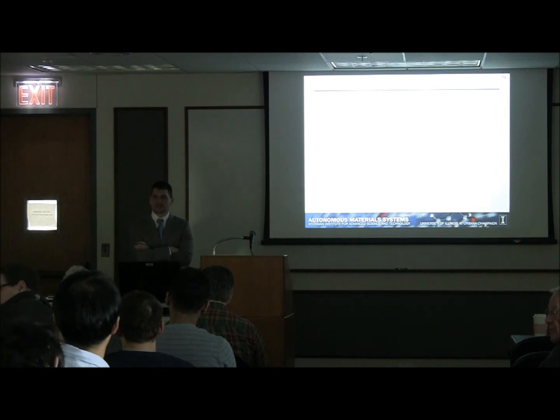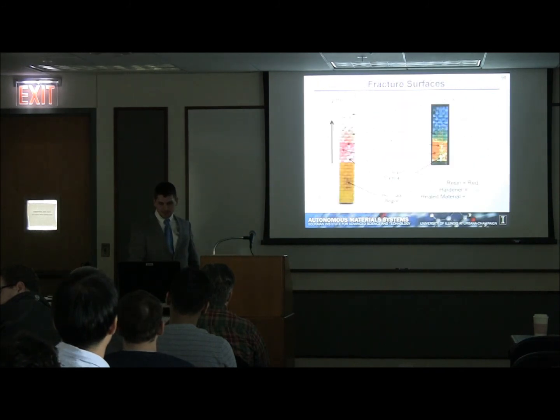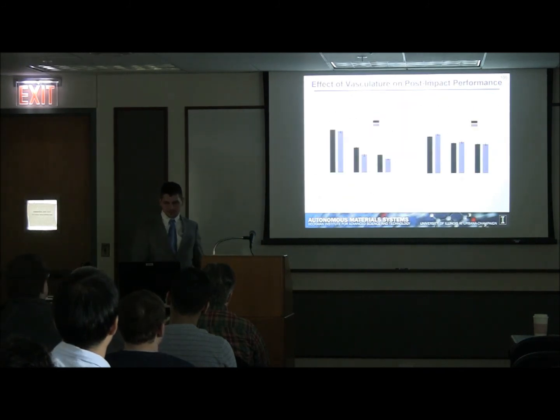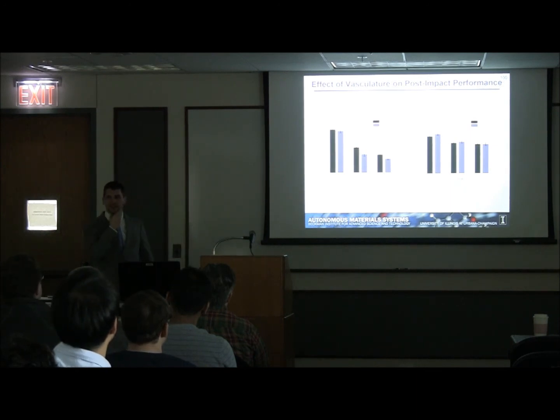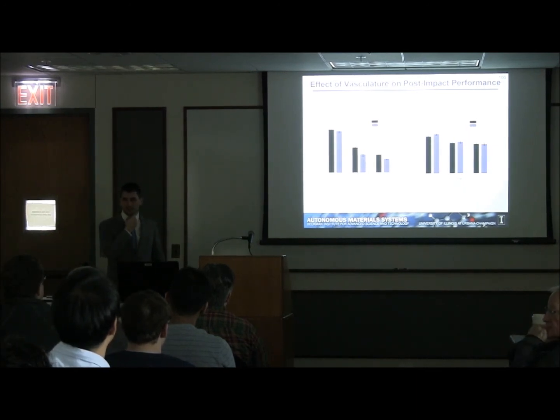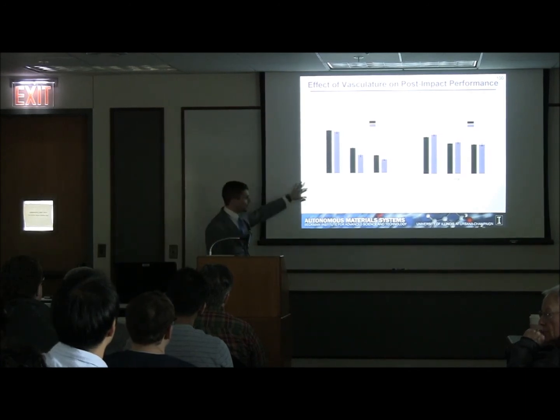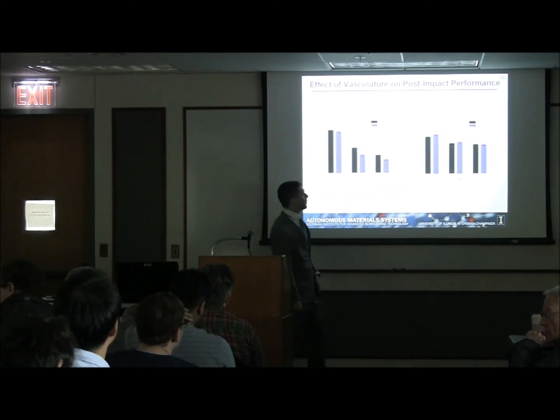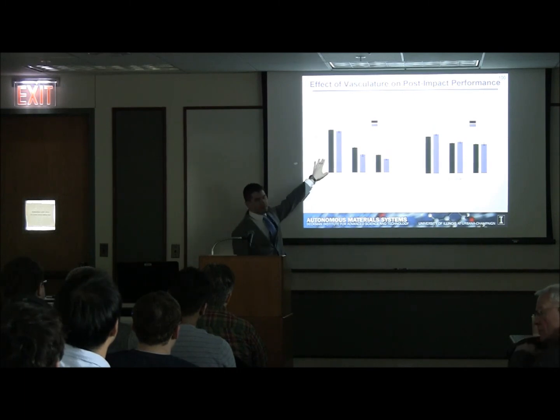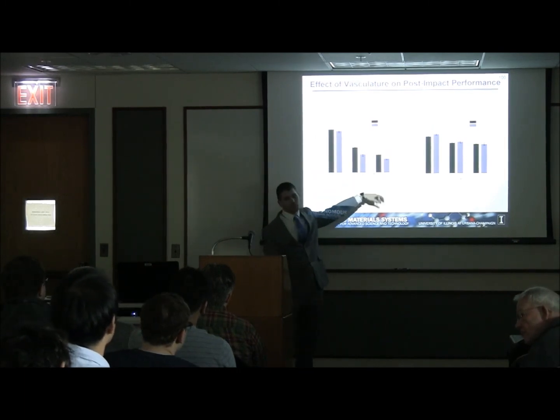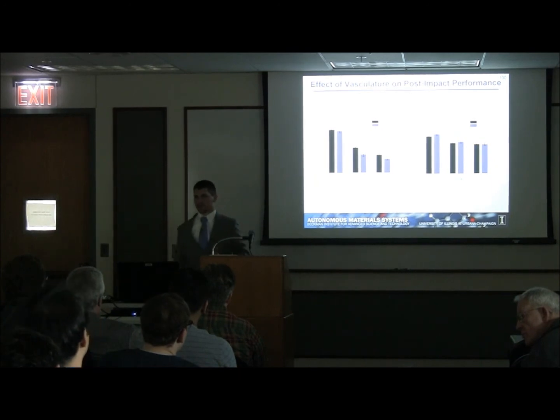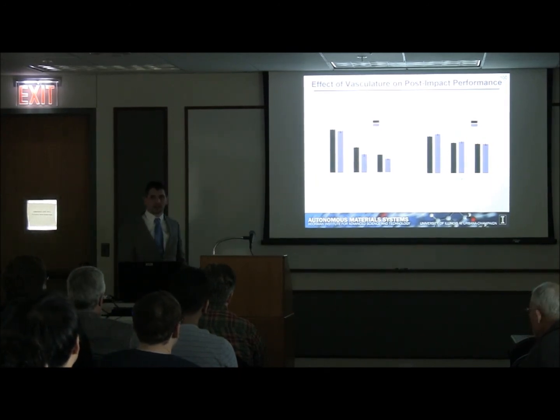Yeah, Paul. Do you lose anything in terms of material capability when you put the capillaries into the composite for the self-healing? It seems like you'd be taking away some sort of strength from that. Yes. I think has some data to back that up. So this is a comparison of unvascularized versus vascularized samples of different impact energies. Here we're plotting the strength as a function of impact energy and the flexural modulus. In the nominal case, not a significant amount, but with the introduction of impact damage, having the vasculature in there reduces the strength substantially.